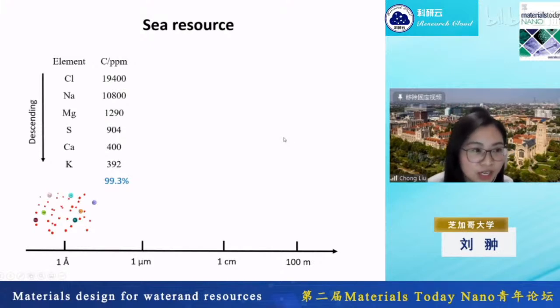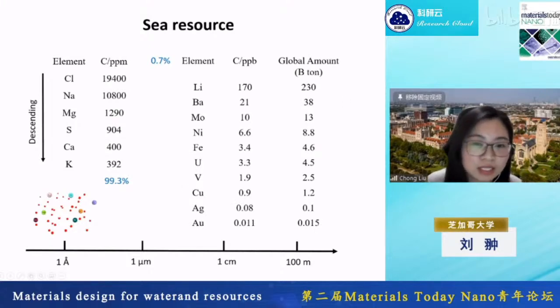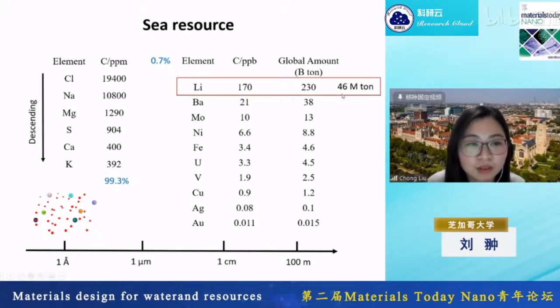And one gigantic source of all these critical minerals is the sea, actually. The sea contains many dissolved ions, and the majority of the ions are like sodium and magnesium, but there are ions that exist in small concentrations in the sea, like lithium or uranium. Those are critical elements. If you consider the total amount of seawater, it holds gigantic reserves of lithium, billions of tons, which is much higher than what we have on land. That's only 50 million tons, so you have thousands of times more lithium in the sea. The challenge of extracting lithium from the sea is that you have to deal with the dilute concentration as well as the competition from the other ions.